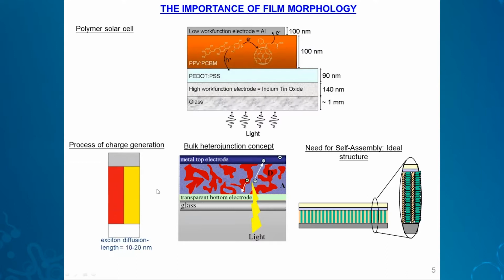Since the time organic materials were used as the active layer in these setups, starting from a single material to a bilayer, the process has evolved, and now the bulk heterojunction concept has come up, where the intermixing of the acceptor and donor materials is done, because exciton diffusion to the DA interface is the most important step. For that, the donor and acceptor should be arranged on a nanoscopic length scale of about 10 to 20 nanometers. Otherwise, if within this length scale the exciton does not see an interface, it will recombine and die, and then it will fail to generate free charges.